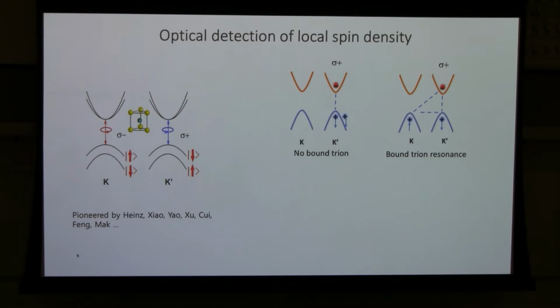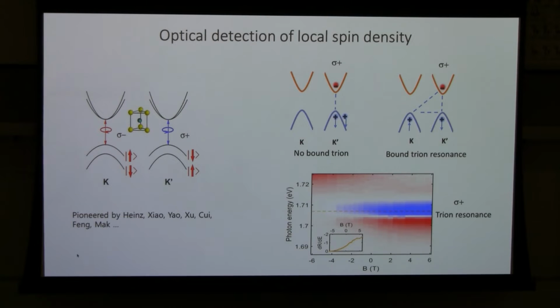On the other hand, if you add a spin up hole in the system, then it has to go to the K valley. Again, if you use circular polarized light to excite excitons in the K valley, then in this case, because these two holes now have opposite spin, they are very happy to form a bound trion state. As a result, by using circular polarization and looking at the trion resonance, you can tell whether the hole is sitting at the K or K prime valley, or equivalently, whether the hole has spin up or spin down. Experimentally, this can be demonstrated by looking at the trion signal as a function of magnetic field.